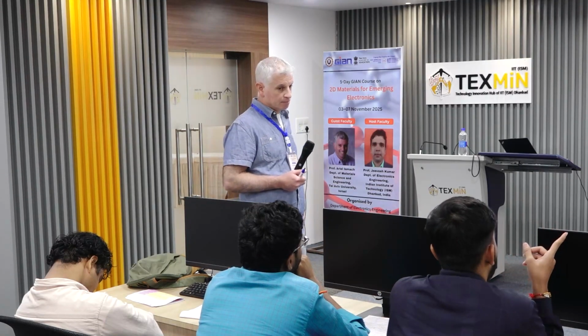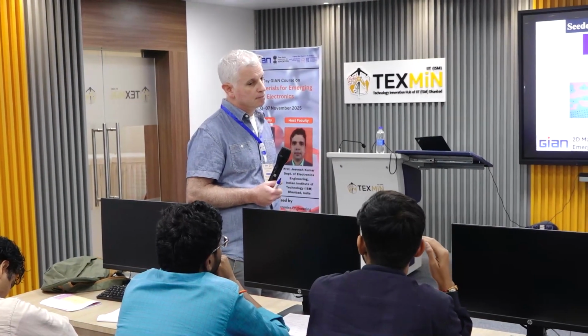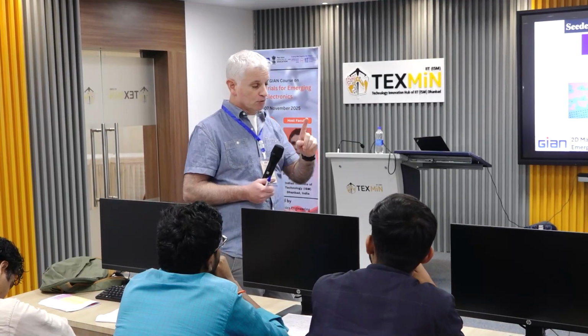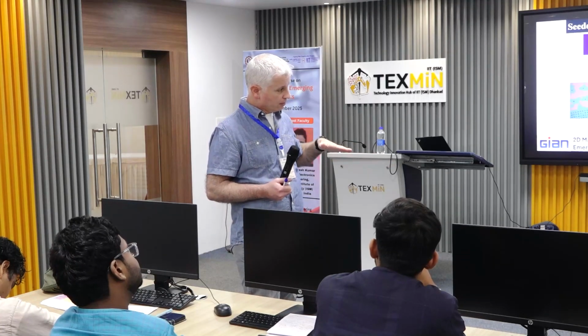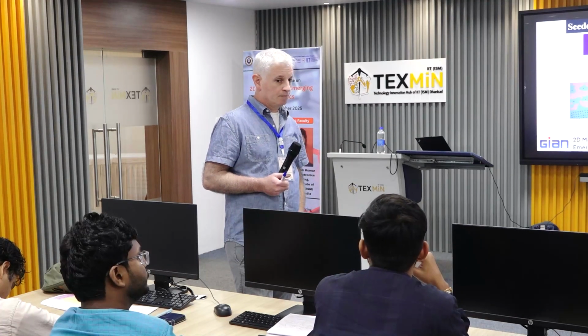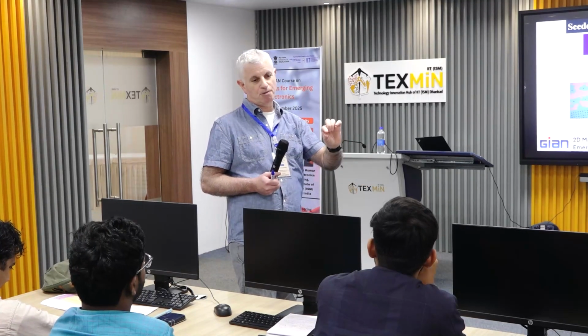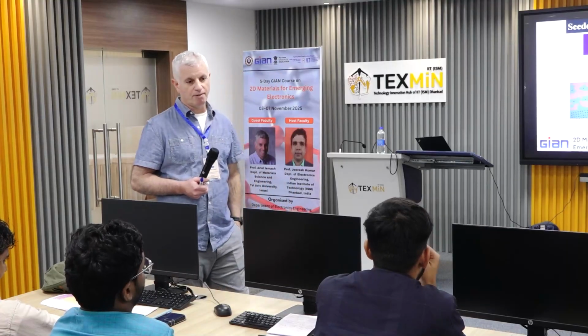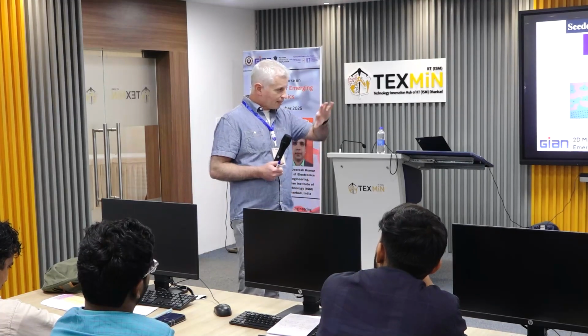And in one case you explained how to control the flow rate or evaporation rate of metal oxide, we use a mica to control the flow rate. No, but this is not to control the evaporation. We don't control the evaporation. Actually, in this case, we let it evaporate a lot. But we control the diffusion of the precursor along the surface. How is that setup made? How is mica suspended? It's not suspended in there. You attach it physically, so it has a few microns gap. This is the confinement. You can build something fancy, but actually mica is not so flat.